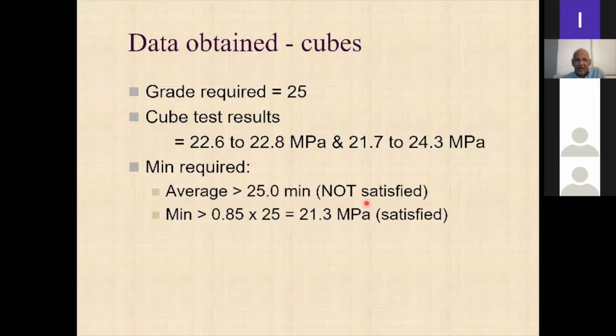So which is not satisfying. I think I know what this is. I think this is 3 cubes from one batch and 3 cubes from another batch, so this is the variation within each of those two batches. So the minimum should be greater than 0.85 times 25. That is a thing given in the SLS standard, that the minimum should be greater than 0.85 times this. So this is the minimum. All of these satisfy that, each cube satisfies that, so that is okay, but the average is not satisfied.